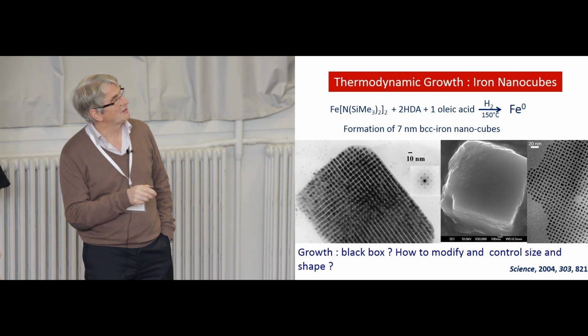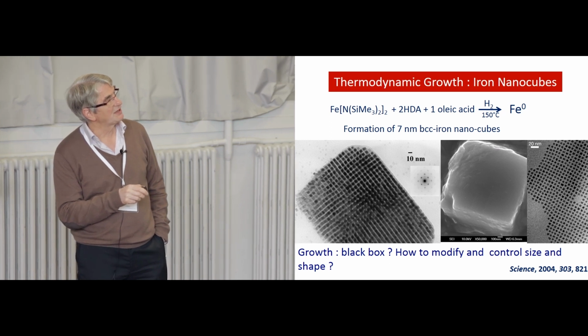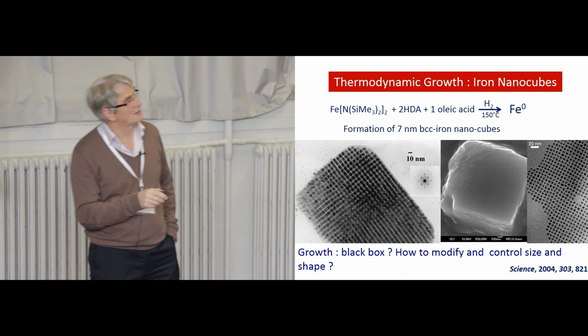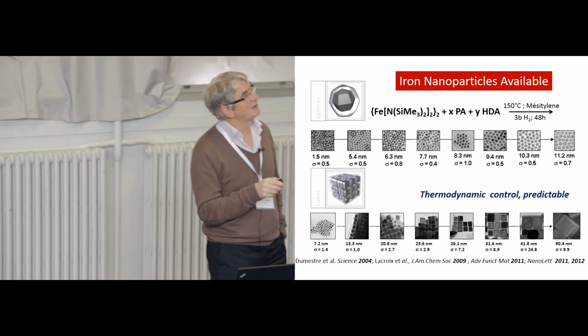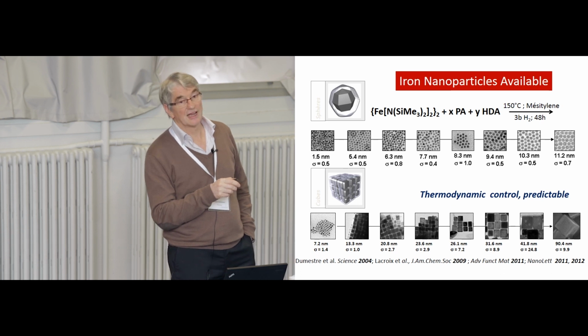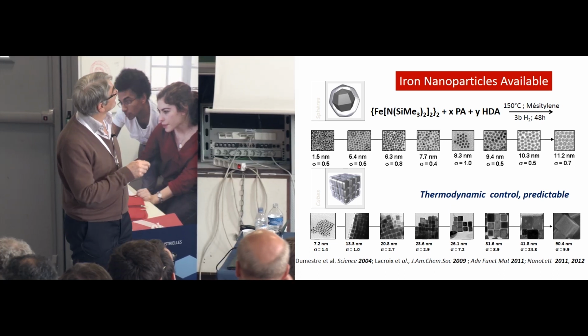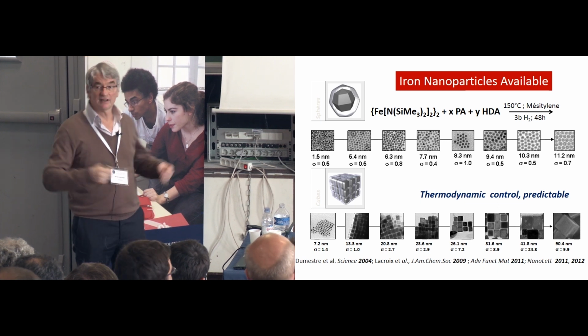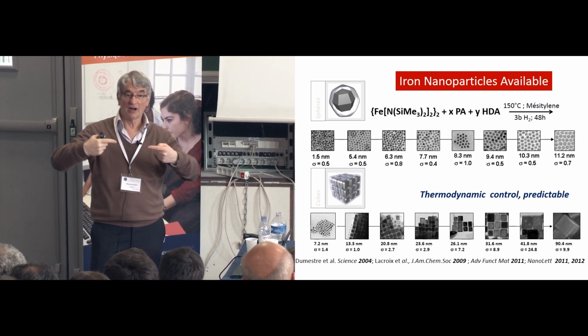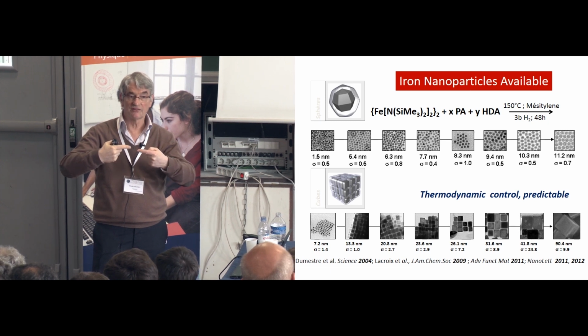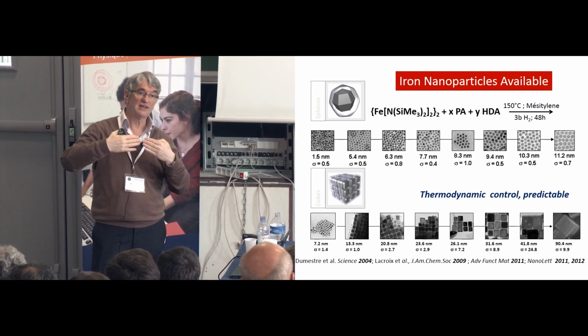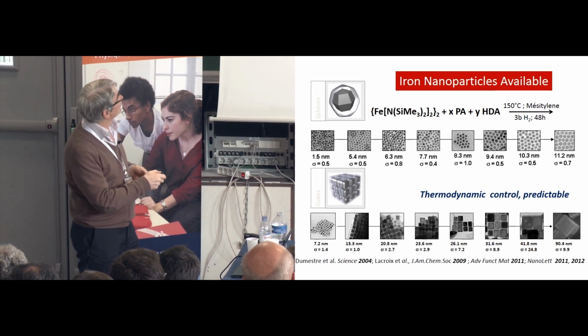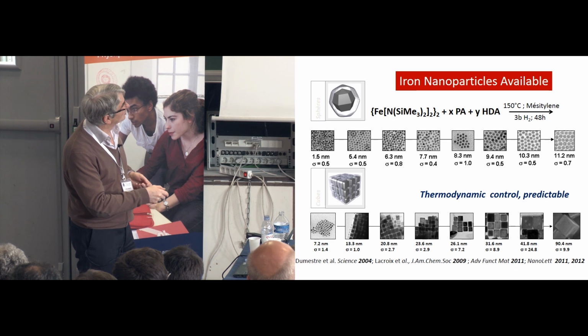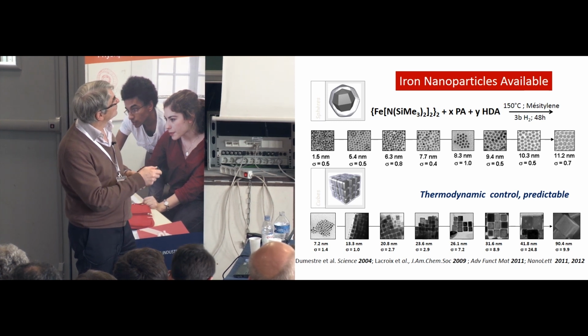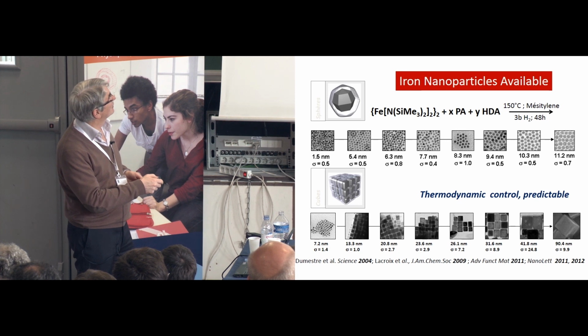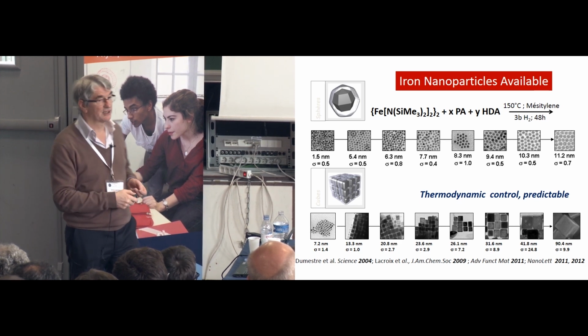What we find is that we put an acid, palmitic acid (C16), and an amine, hexadecylamine (C16) also. Depending on X and Y, the more we put palmitic acid, the less we will form an iron 2 complex with 2 carboxylates, and we will decrease the number of nuclei. So the more acid we put, the larger particle we will get. And the more amine we put, the easier we will decompose the particle.